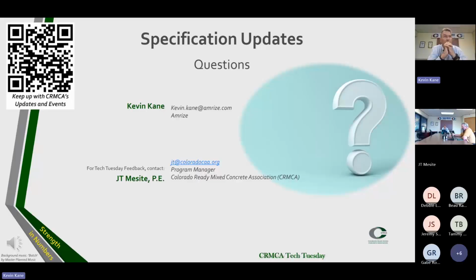I'll actually add to that, Kevin, in regards to the question of how do you reduce that variability. It's something that you had said, and we continue to say in almost all of our Tech Tuesdays, is having the conversation up front. At the pre-construction meeting, have that conversation, because we've seen it through our CTAC program that's run nationally, and through our test fests over many, many years: the initial curing is one of the leading causes of questionable concrete results. If we're able to reduce those questions just in the initial curing, that variability is going to be reduced. But that's one of those steps, just having that conversation right at the beginning.